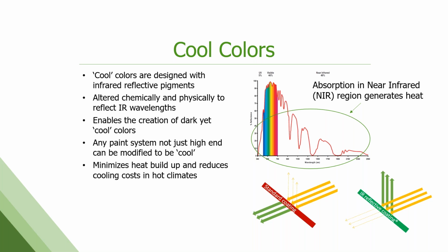Any paint system can be modified to be cool. It's all about the pigmentation, doesn't have anything to do with the resin or the polymer. And it does truly minimize heat buildup and reduces cooling cost in warmer climates. And actually, this has really become standard. Most paint companies, especially in the PVDF or the Kynar paint lines, are formulated with these cool pigments as a standard. You don't have to request it anymore. It's become the norm.